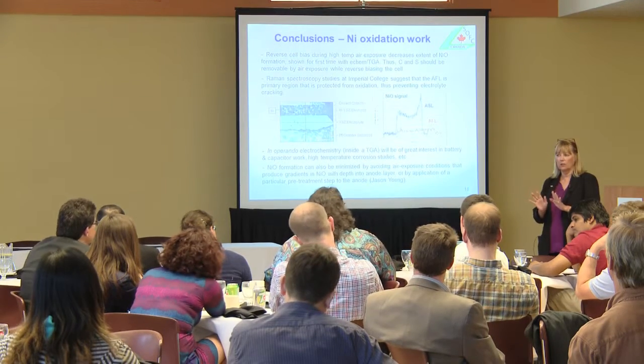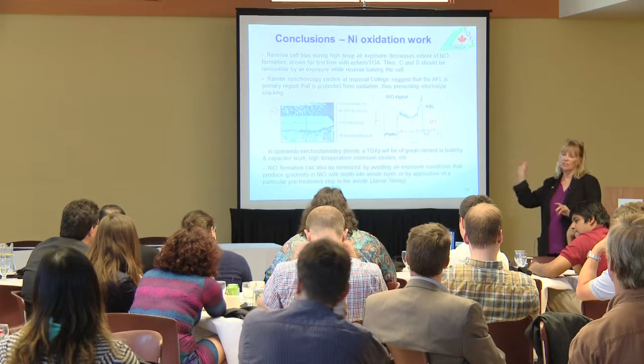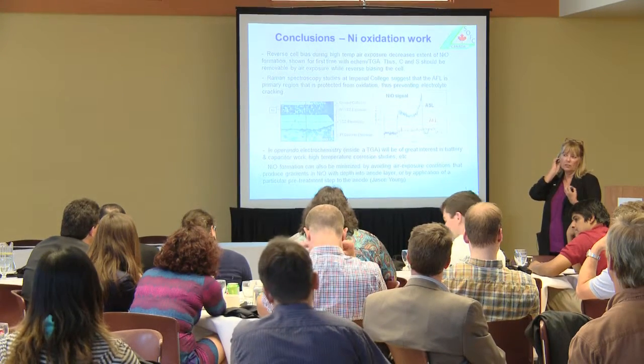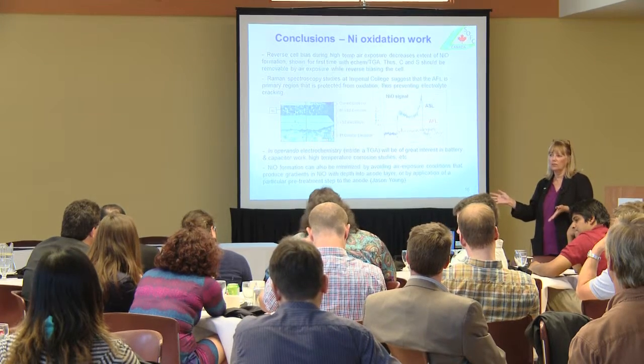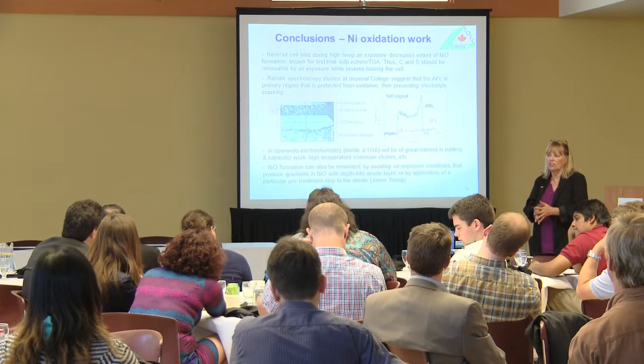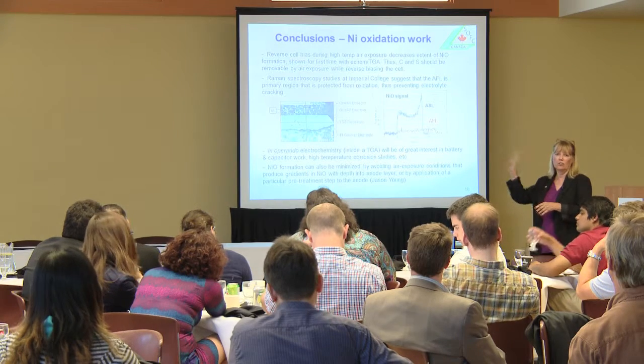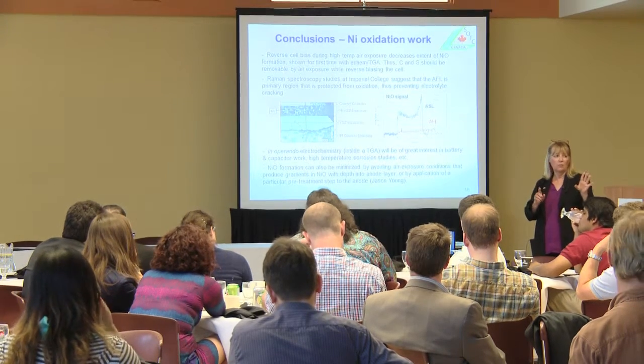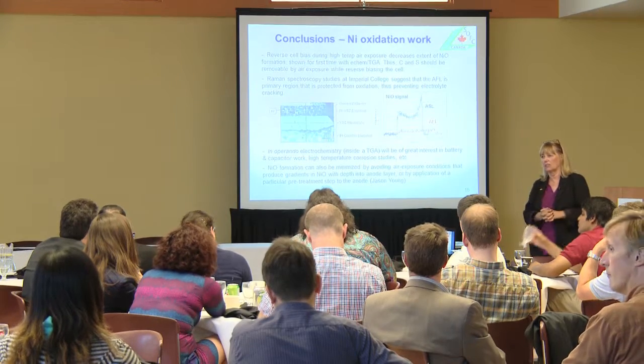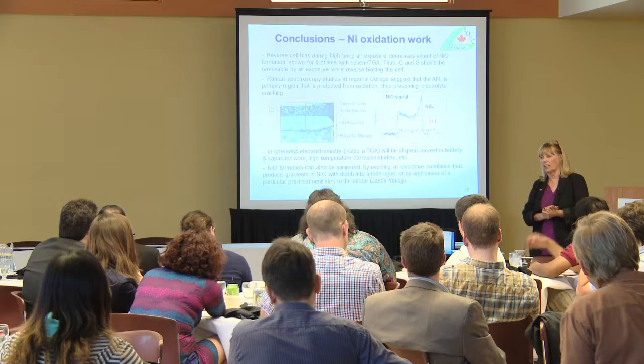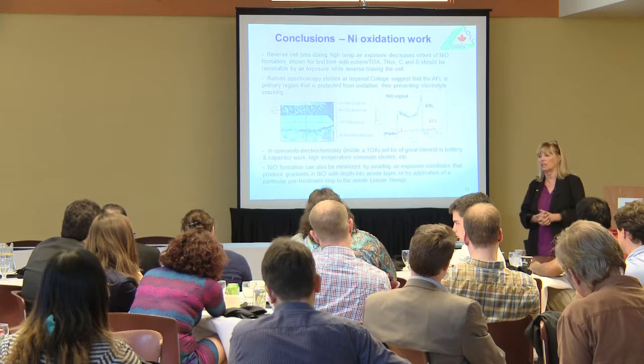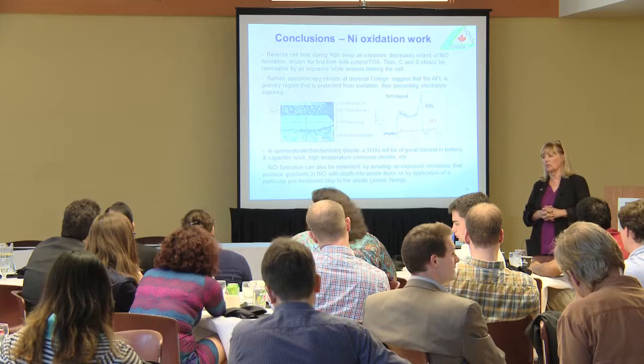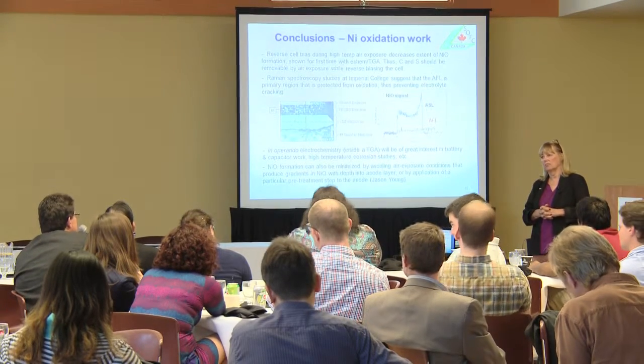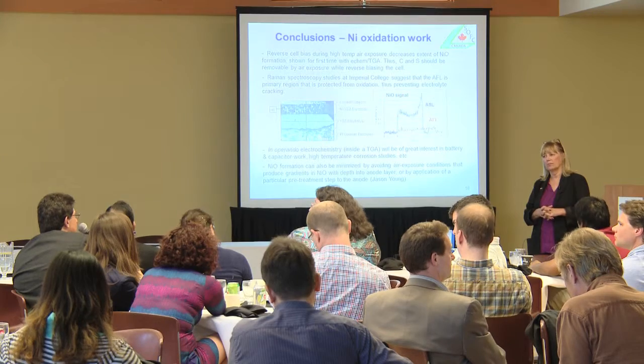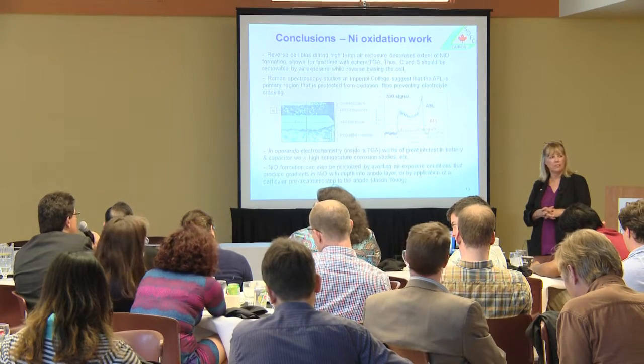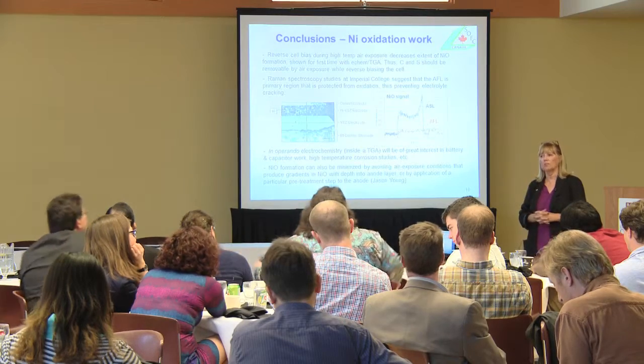Well, we haven't done the carbon work. We're not doing that kind of carbon work. Here we only see that what oxygen will do is remove the sulfur. Whether it changes the nickel structure, that's not clear. Now, I took the bullet out because I just knew I was going to run out of time. We have other work that has shown exactly what you said, that sulfur will stop coking in CO environments, syngas environments. So that's true, and we have other fresh results. But the exact mechanism is still not very clear in the literature. Probably not. There are just assumptions, speculations, but not clear evidence of that. Thank you very much. We have good evidence, but probably the explanations aren't fully clear.